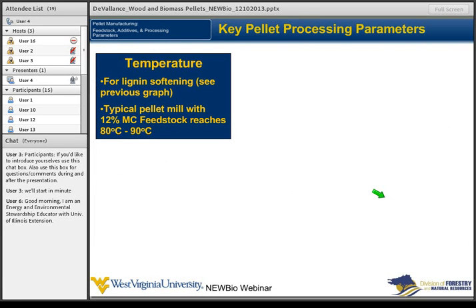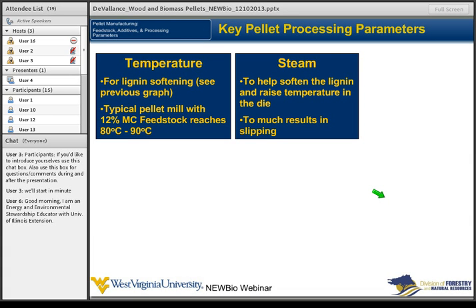So some key processing parameters in making pellets is temperature. As we discussed before, we really want to get that lignin to soften. If we're looking at a typical pellet mill, the temperature inside there gets about 80 degrees C to 90 degrees C if you're at 12% moisture content. So for lignin softening, it's still, in a lot of cases, a little too low depending on what material we're looking at. So if that happens, we use steam a lot of times to help soften the lignin and raise this die temperature. And one thing that it can cause, though, if you have too much steam, is slipping of the die.